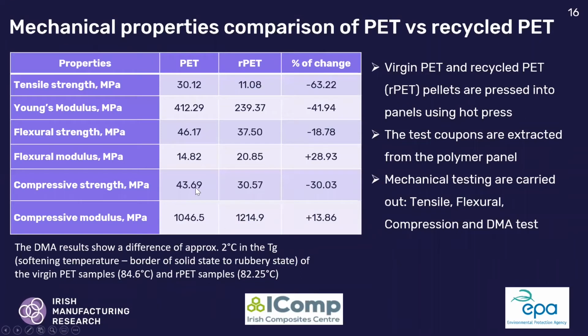As a part of the project, we did a comparison of PET with recycled PET in pellet form. Both pellets were pressed into a panel by using a Collin press at University of Limerick. Then we extracted samples for the tensile test, flexural test, and compressive test. The results are given in the table, and it shows that except flexural modulus and compressive modulus, all the remaining values are decreasing compared to PET. This means the recycled PET shows lower values.